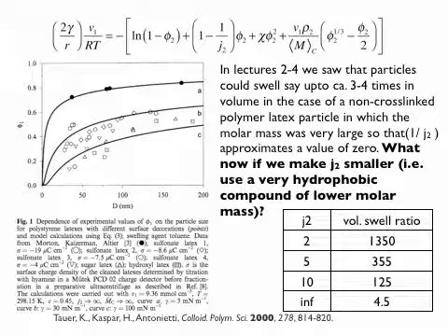Yeah? What happens now if I make this polymer way shorter? So I don't have high molecular weight polymer, but a low molecular weight system. So what now if J is 5 or J is 2, so a dimer of styrene or a pentamer of styrene, or just another small molecule that roughly takes up in space 5 times the volume of styrene? You'll see that the volumetric swelling ratio shoots up, which means that material would love to attract more monomer,